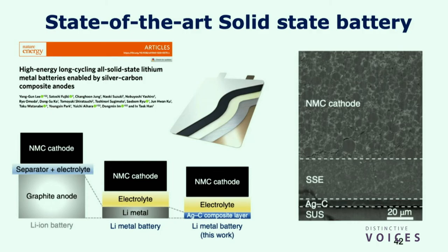They are making a solid-state battery that performs quite closely to a lithium-ion battery, I'll say. And it uses the holy grail electrode, lithium metal. These are pouch cells. If you take a standard lithium-ion battery drawn to scale, this is their battery. This is a cross-section of their solid-state battery. It's a sulfide-based material. Sulfur is cheap. Lithium, sulfur, phosphorus, and chlorine, that's what it consists of. They have an NMC cathode, so it's a composite. The dark phase is the cathode. The light phase is the sulfide electrolyte. Here's a solid electrolyte, the sulfide. And they have this magic silver carbon. Silver is not economically viable, but it works well.